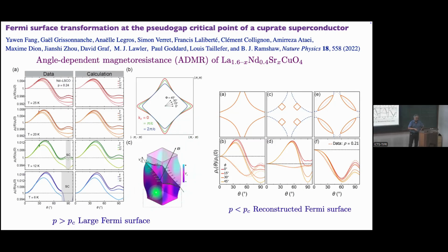All the electrons are moving in the AB plane here. And then you measure how the resistance varies as a function of the angle. You model that through a simple Boltzmann equation of electrons moving along the equal energy surface orthogonal to the magnetic field. And from that, you can read off how the magnetoresistance will change as a function of angle.